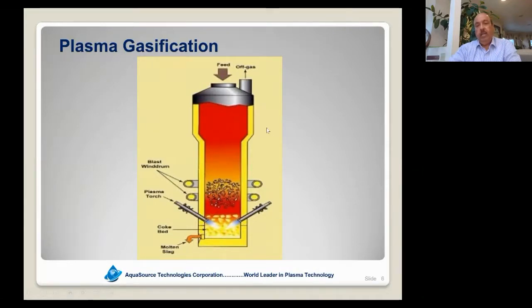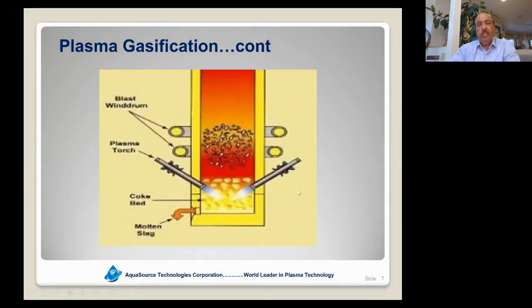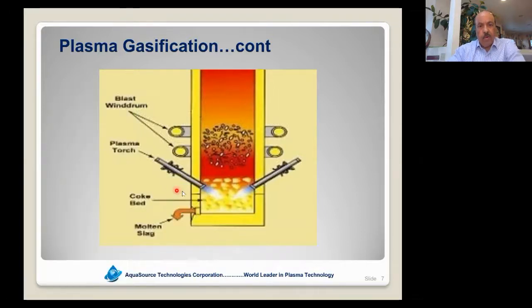In this slide, you see what we call a foundry cupola. It's a regular furnace using standard refractories, and it has regular steel components, valves, and stuff like that. And the plasma torches that I mentioned before are applied in the bottom section here. As you can see in this bigger picture, if you can see my arrow, let me make it into a laser pointer. In this area, the temperatures are in the 3000 to 5000 degrees centigrade range, far removed from the refractory.